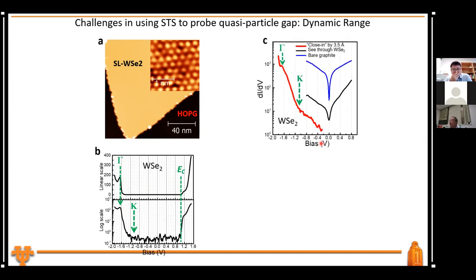You prove it. So we first prove this by taking a tunneling spectroscopy at your typical tip-to-sample distance. Then, after interrupting, we artificially put the tip closer by 3.5 angstrom. Then when we look at the tunneling spectroscopy, what used to be this sharp feature has now become a shoulder, and then there is another shoulder coming in. But how do I know that this is not the underlying graphite? Well, if I look at graphite, this is what I observe. If I put my tunneling bias inside the gap, then this is what I observe by seeing through WSe2. So we know this is graphite. And then up to here, there is another threshold turning on. Then it's clear that this is where the onset of the valence band maximum is located.